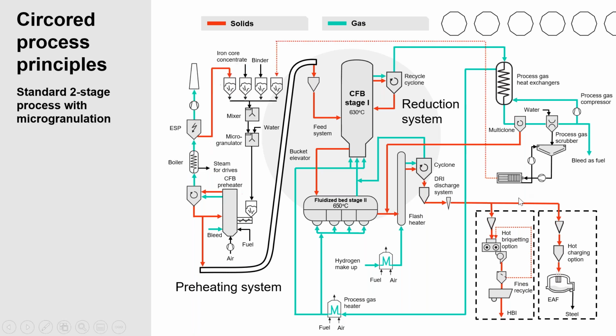In this case, iron ore pellet fine concentrate is fed together with a binder to a mixer and subsequently microgranulated under some water addition. This process variant brings the advantage to recycle the dusty material reclaimed by the scrubber system. The green granules get then fed into the preheater for hardening. The downstream process route remains basically the same.